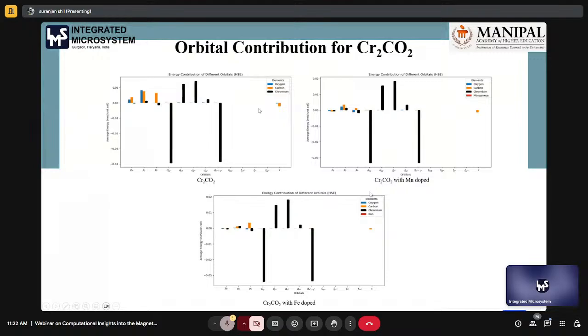And also you can see here that in the structure without doping, we have very negligible contribution from the oxygen. But here we can see a significant contribution from the oxygen, which signifies that after doping with manganese, the hybridization of the atoms changes and different orbital contributions mix up compared to the undoped material. Here in the case of iron doped materials, this energy also increases, and also the significant contribution comes from the oxygen compared to the undoped materials, but it reduces for carbon. You can see here in the undoped there is a significant contribution for carbon, but here there is very little contribution compared to the undoped one. That means oxygen increases but carbon decreases, and here is also this oxygen in the positive direction. That means it's a vacant orbital, it gets stabilized, it gets filled.